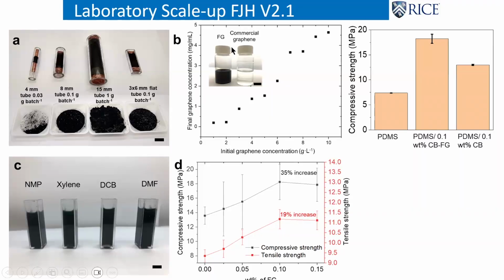But if you want to make bulk graphene that you can now blend into materials and put in composites, that then has this big effect. You can see that if you buy commercial, quote-unquote, graphene and try to suspend it in water and then centrifuge it down, it just all drops to the bottom and you can decant off a clear liquid. Here you do the same thing with flash graphene and it stays dispersed. That means these are really well dispersed sheets, and then the surfactant was able to get in between them and keep this suspended in water.